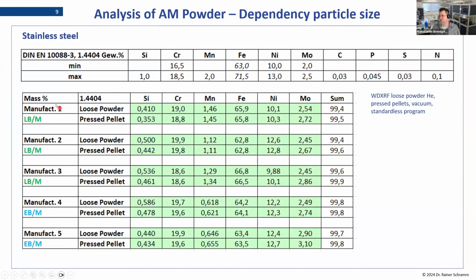And so what we see here is for all 5 materials, we have the loose powder on top and the pressed pellet, and we use the same standardless software to analyze this on our wavelength dispersive unit. So standardless meaning we just told the software what this is, and then the software made the analysis for us, and it's the same program that does the analysis. And as you can see, the differences between the pressed pellet and loose powder are quite small. So in general, what we can say as a conclusion is there are some systematic effects you can see, but mainly in the small components, and that is based on the calibration itself. The loose powder obviously has a film and so on, so there are a few effects.